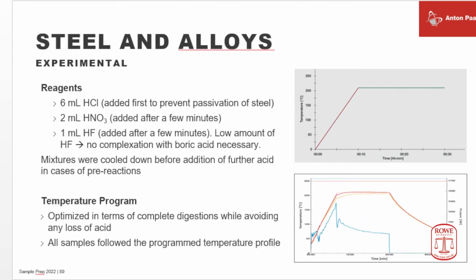Important when you add the reagents to steel and alloy sample, add the HCl first, because if you put the nitric acid on first, it would lead to a surface passivation of the steel material. If you do the hydrochloric first, it already starts attacking your sample before you start heating. Some samples may require the addition of hydrofluoric acid, and you will note that when you add the acids, there will be some reaction starting immediately with the steel samples, and you should wait for the first reaction to decay a bit so it cools down a bit, then add hydrofluoric acid, close the reaction vessel and go.